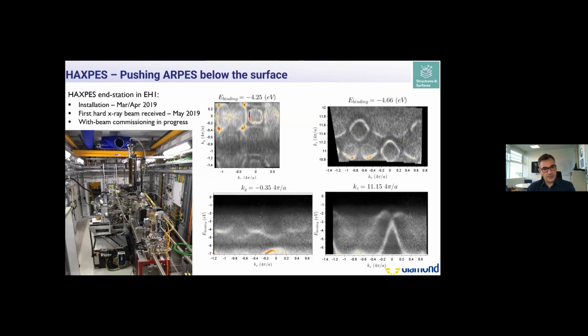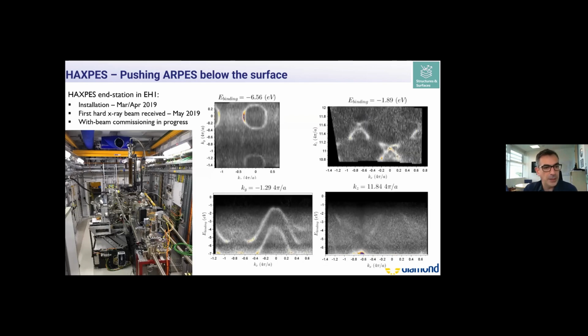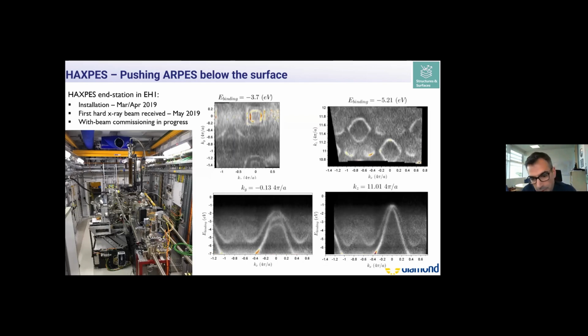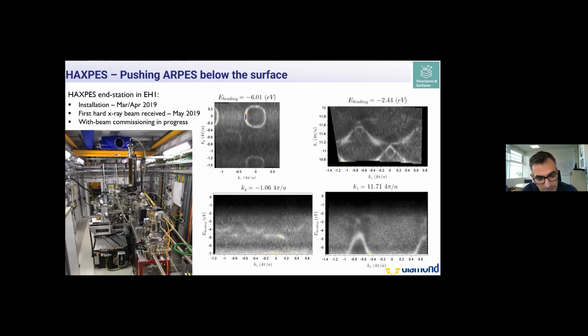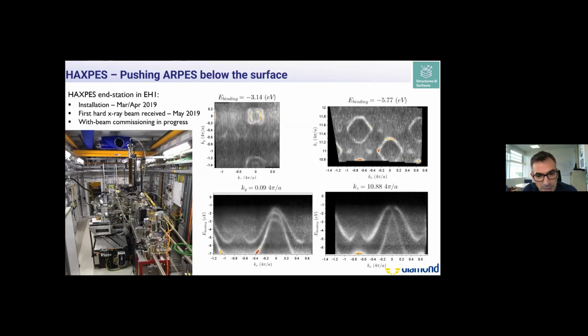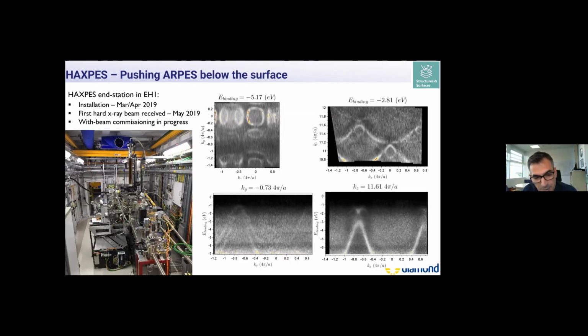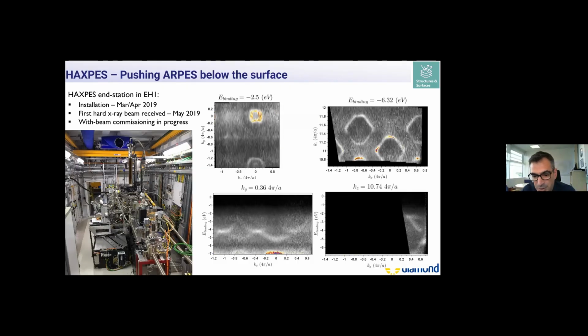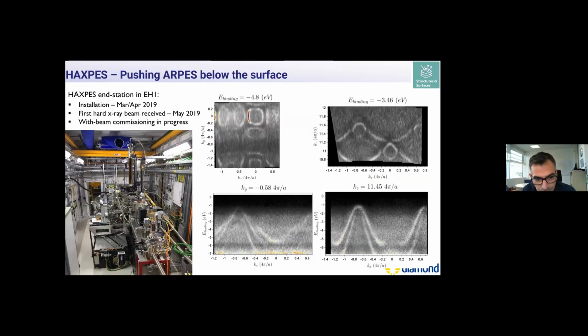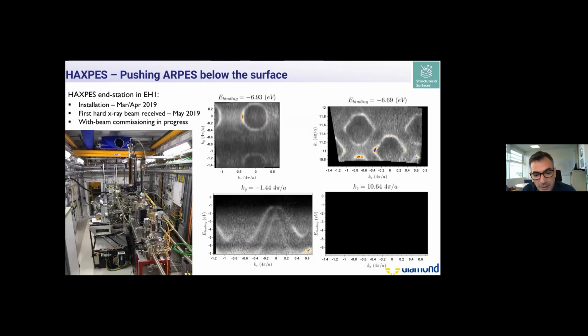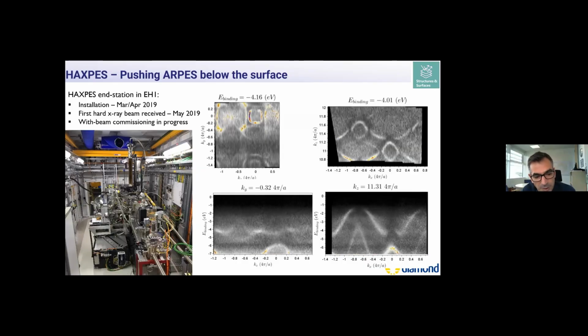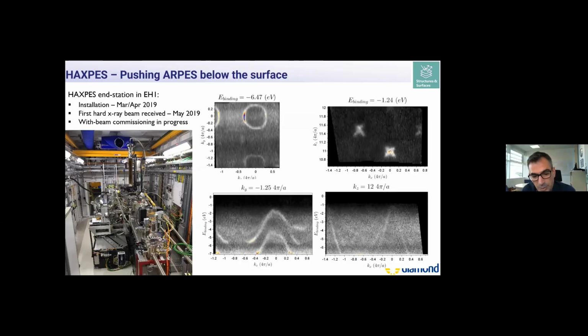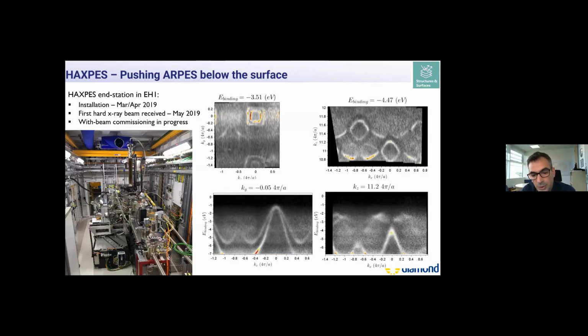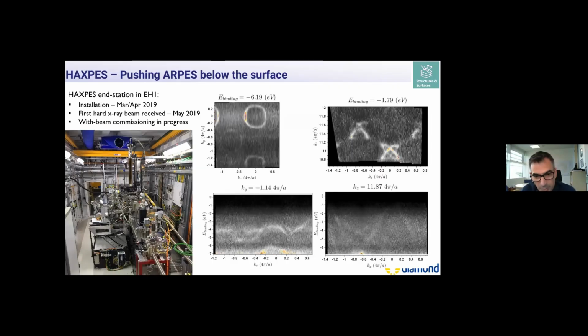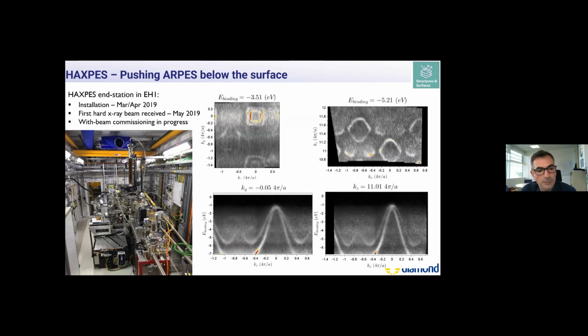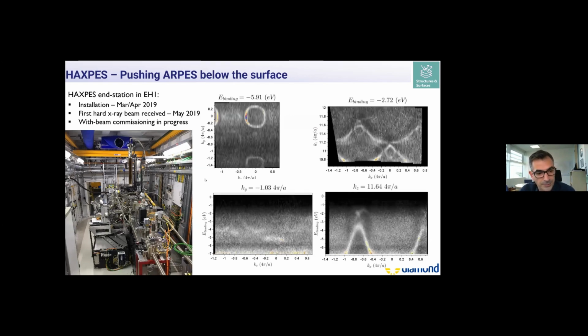Continuing with ARPES in the surface group, we've also recently added the capability to do higher energy, so HAXPES and also soft X-ray ARPES. And this is a very nice capability in the sense that you can really probe this 4-dimensional momentum energy space without having necessarily access just to the surface, but probing matter which is deeper than what you can do with UV ARPES. You're not so sensitive to the defects of the surface, which opens up opportunities for many different applications.